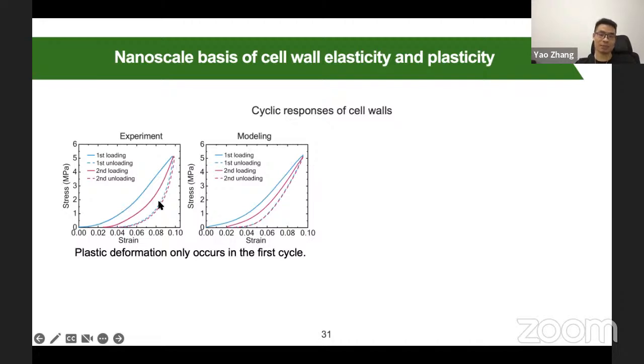If you look at the stress-strain curve of the two cycles, you will find that the first loading process, the solid blue line, is different from the loading line of the second cycle. And if we continue to do cyclic loading, the third cycle has the same stress curve as the second cycle. So only the first cycle has a different loading curve. It's just the solid blue line.